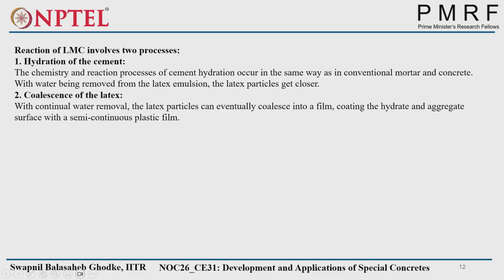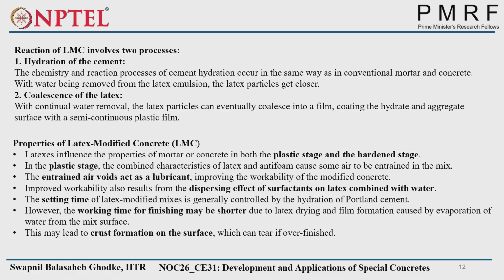With continual water removal, the latex particles can eventually coalesce into film, coating the hydrate and aggregate surface with a semi-continuous plastic film that will fill the voids in the concrete matrix. So, what properties do we get with this type of concrete? It affects your properties in the plastic stage and hardened stage.